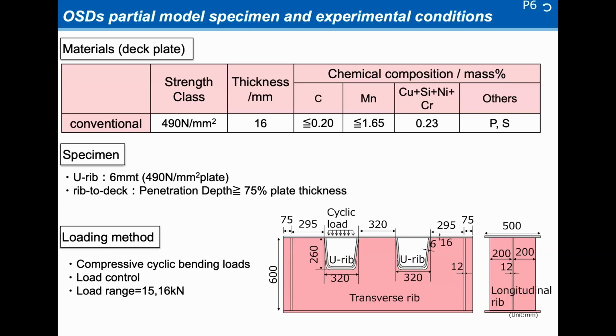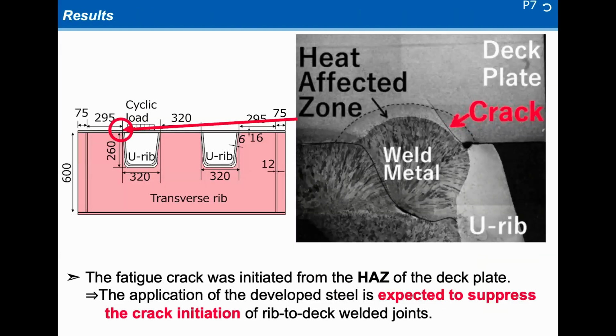Loading method: compressive cyclic bending loads and load control. Load range is 15 and 16 kilonewtons. This is the result. As shown in the photograph, the fatigue crack was initiated from the HAZ of the deck plate. So the application of the developed steel is expected to suppress the crack initiation of rib-to-deck welded joints.